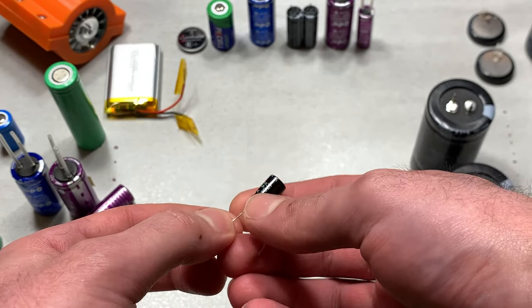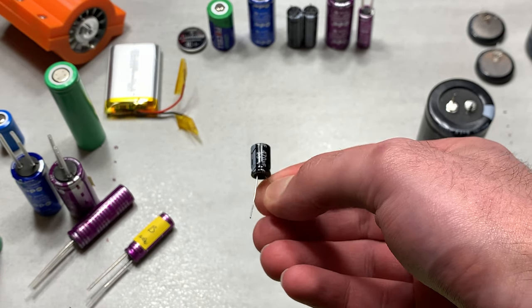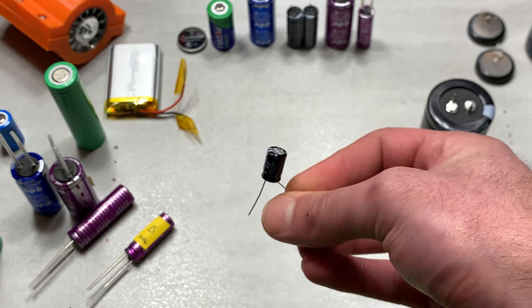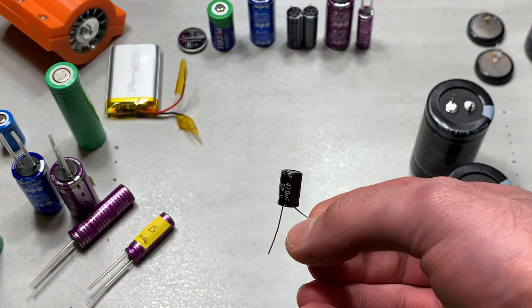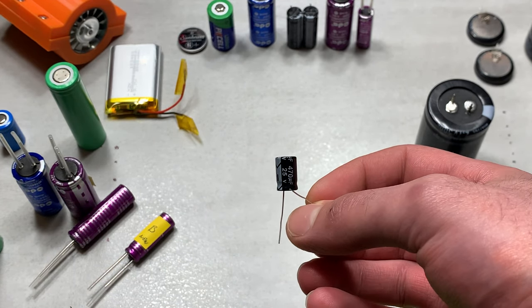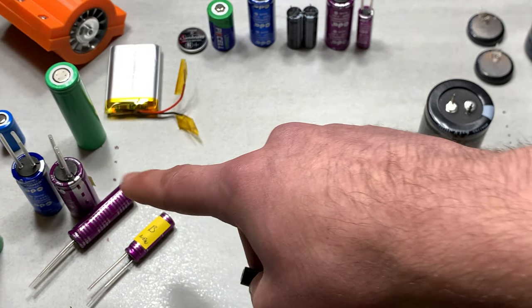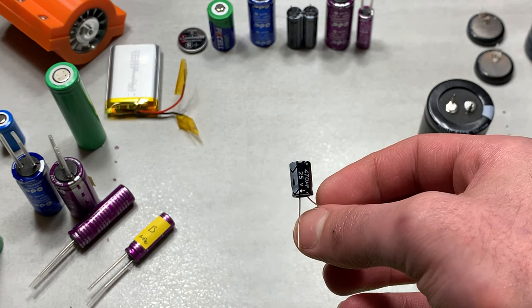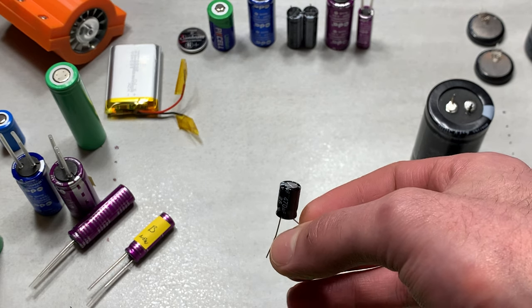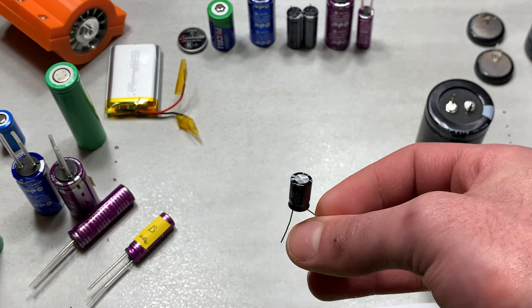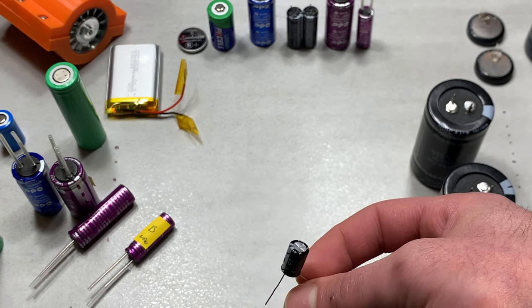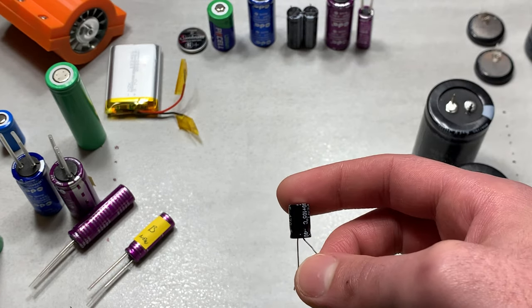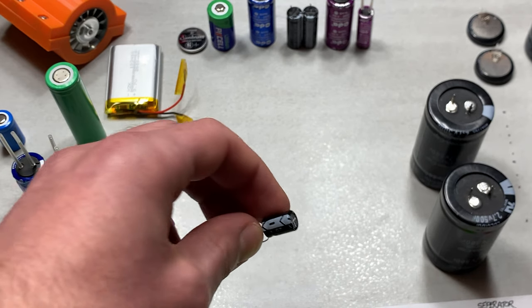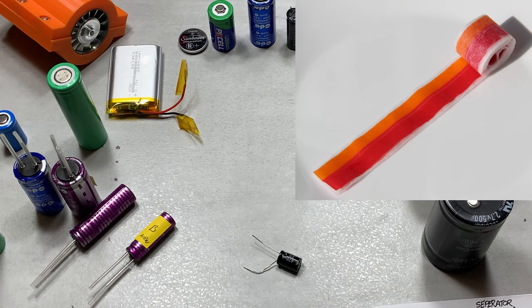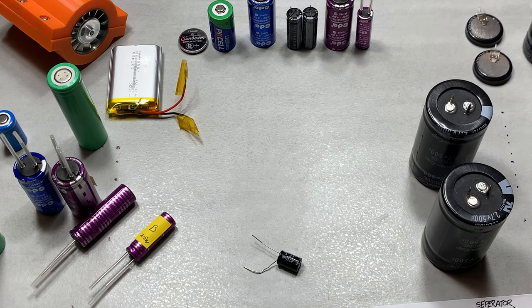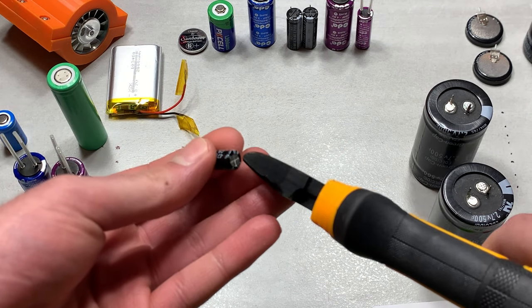it leads me to make the, again, educated guess, I cannot know for sure, that the higher surface area of the electrodes and separator, which would most likely be present in such capacitors, would lead to a decrease in current density, therefore allowing for much, much higher relative charge and discharge rates per cell, something which we're going to get into in just a second, right after I open this capacitor up to show you what I mean. That the inside is made like a fruit by the foot roll. And yes, I should be wearing gloves for this, but I cannot find them.